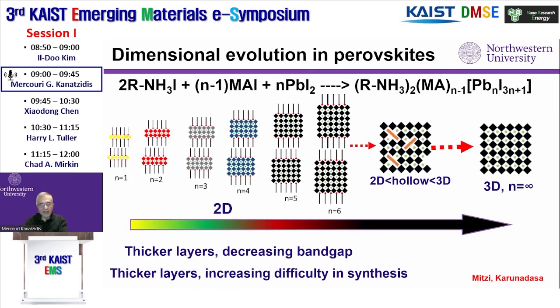Now, chemistry, of course, can be changed, and you can do synthesis of derivatives. If you add an additional organic cation that is too big for the cage, and you mix now, you have two cations, something that does fit and something that doesn't fit, you can actually make a series of two-dimensional perovskites. And these have a slab that is a perovskite, and then the slab is separated by cations, the long cations, which act as spacers.